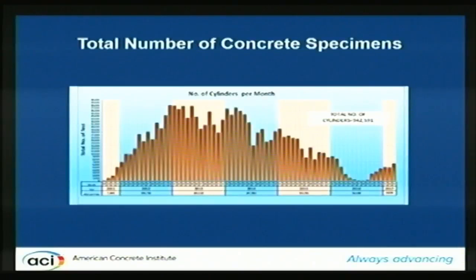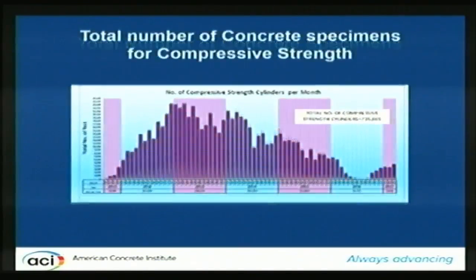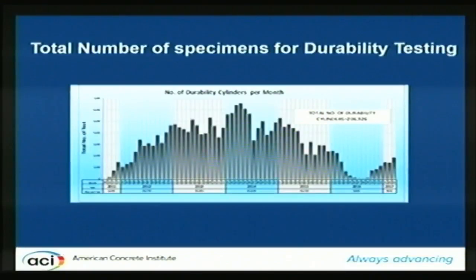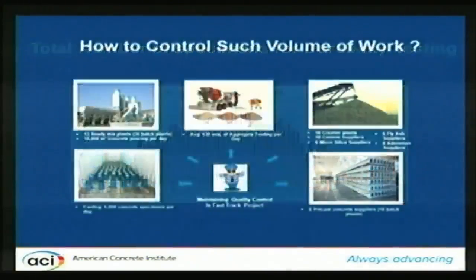The concrete specimens, we reached 1,500 cylinders per day, some of them taken for compressive strength, some of them taken for durability. The chloride permeability, the absorption, all these tests were done also in parallel. So the scale is really staggering. And when you have something like this, you cannot manage it the way we used to do a few years back with papers. You need systems. You need management systems that take care of that.